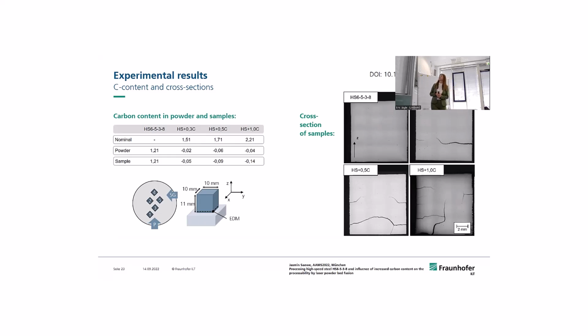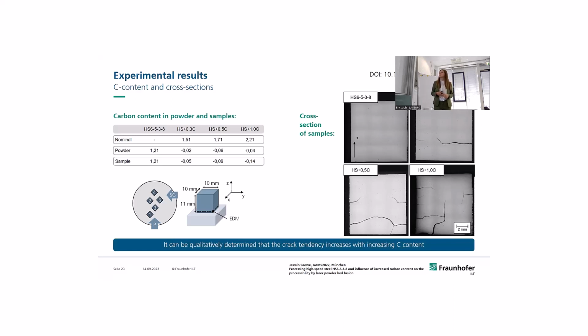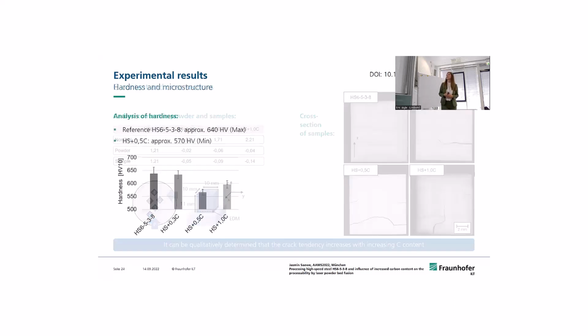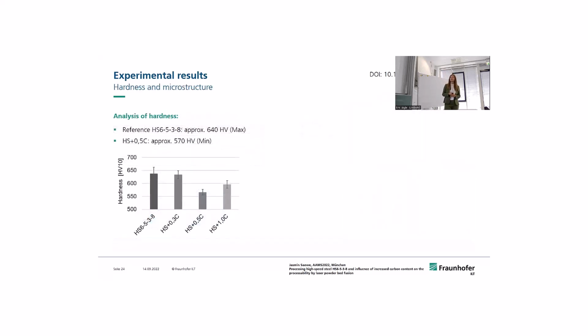Cracking was not prevented, but induced, which was something that we expected, and something when we already have a crack-free specimen in the beginning, how would we prevent it even? But it was just looking into it, if it's feasible or not. So why is it cracking? That is the interesting question. And looking into the material, we first determined the hardness. And what is interesting is with higher carbon content, we lower the hardness of the material.